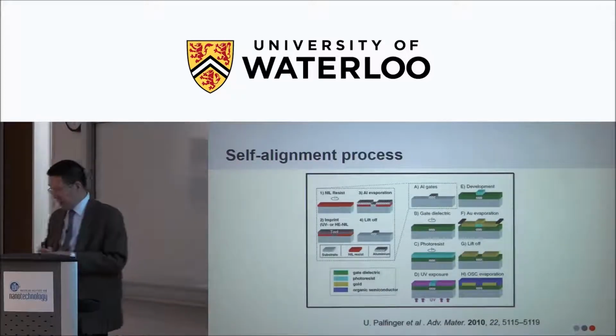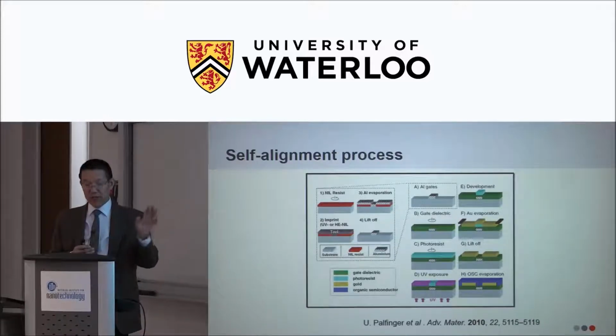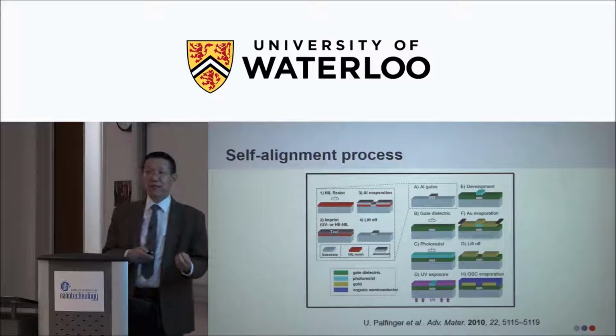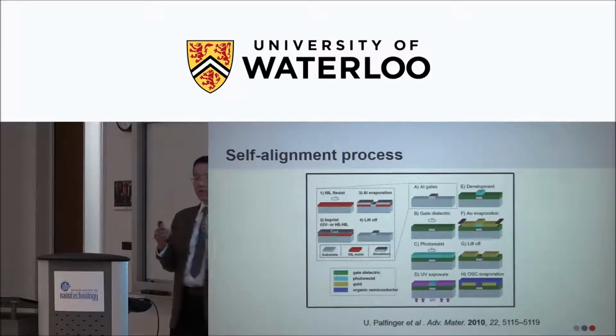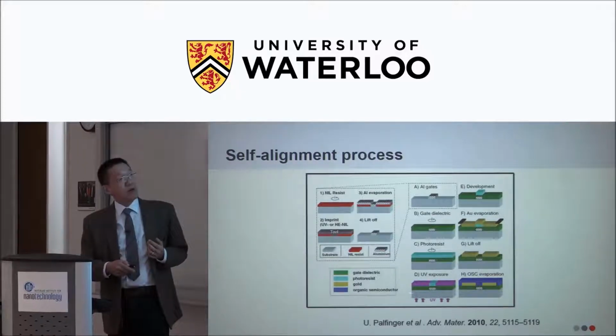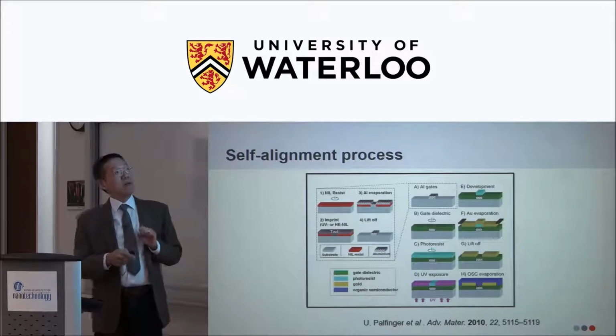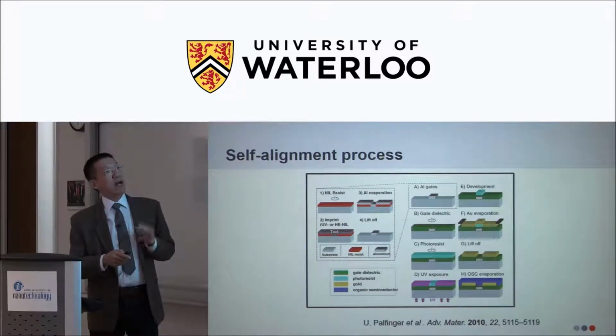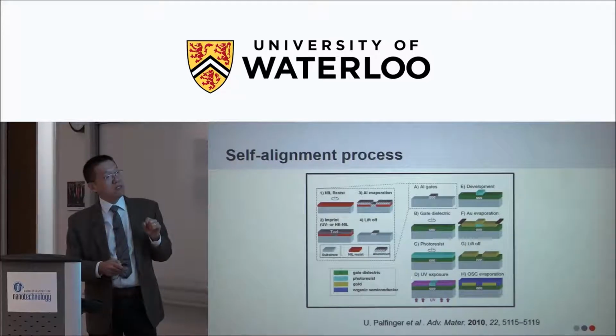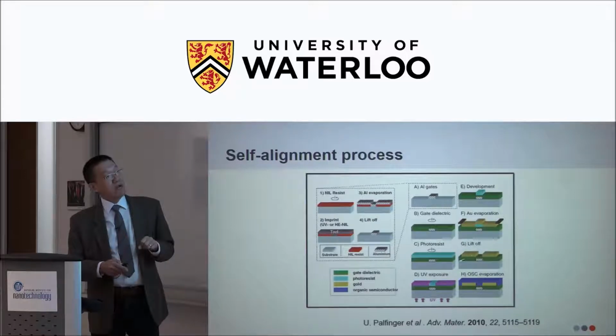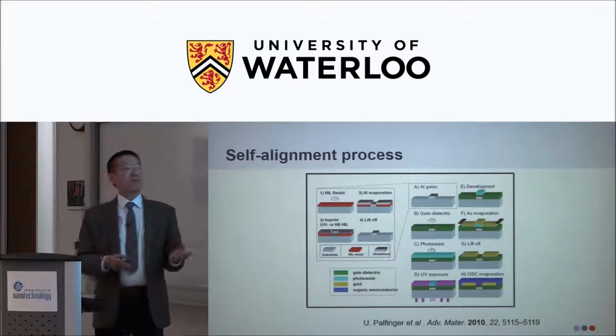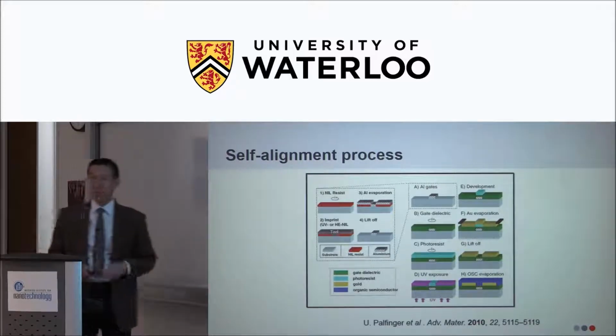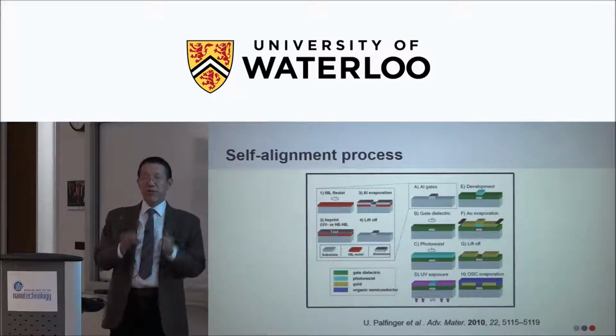There are people who developed a process in Europe, and Palfinger's team did a lot of work on self-alignment processes. The idea is to use a photolithography process to align the gate metal with the source drain electrodes. Basically, you use a nano imprinting process to make a highly well-defined gate first. Then you put dielectric on, put a photoresist, and use a laser process to define the photoresist area. Then you evaporate gold on top of it, then lift off, and there you have a well-defined source drain on top of the gate. But that process needs vacuum deposition. It's a very complicated process. Very elegant, but difficult. It's not compatible with the printing process.